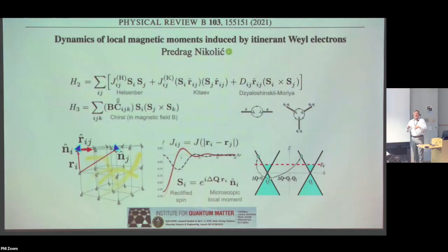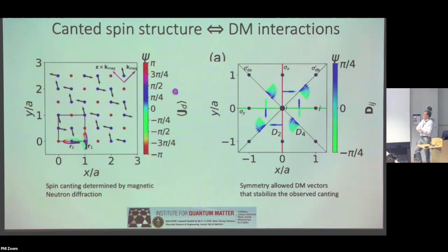But actually what we find experimentally is that it's the perpendicular to bond direction which is strong and important for the magnetic structure that we observe. So this was a theory stimulating being able to extract these things. But now we see experimentally that it doesn't have the simplified form. And Predrag understands why that is. That's because in this theory, the crystal structure doesn't really exist at all apart from just the two Weyl points. And so the lowering of symmetry that takes place in the crystal structure is not taken into account in this theory. And so he has worked and I think has developed a more advanced version of that. So this is the interplay between the theory and experiment that you would expect.